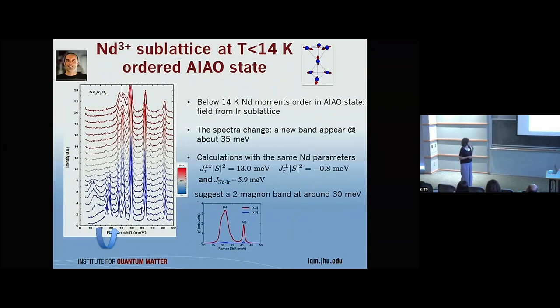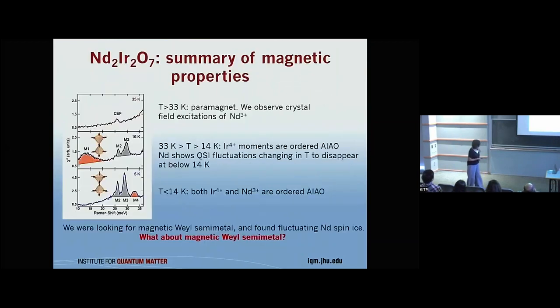And then again, Natasha and Yang did more calculations of what the magnetic spectrum would be for neodymium all-in, all-out. If they take the same parameters and the previous Hamiltonian and add this local field, then they reproduce the mode which we have here. So it's again a fit, but in a way it's a restricted fit, because the first set of parameters agrees with both states. So what we think we observe is, in terms of magnetic excitations, what happens with these magnetic sublattices.